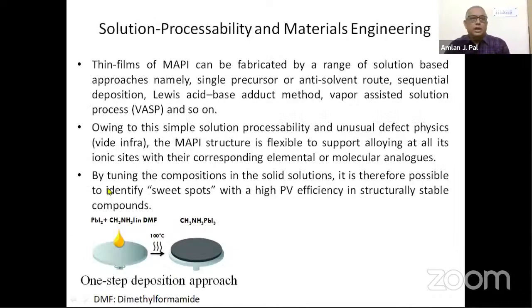Solution processability, that is the other part, that is you can make this particular material in the lab. There are two methods, what we call the one-step method and the two-step method. So thin films can be fabricated by a range of solution-based approaches, single precursor, sequential deposition, and so on. And because of the simple solution processability and unusual defect physics, which I will explain later, we can find some kind of sweet spots. These sweet spots will give me very high photovoltaic efficiency in structurally stable material. Just a little on how we make it, because being in device physics, I cannot just rely on materials or thin film fabrication by others. So we have to do it in our lab.